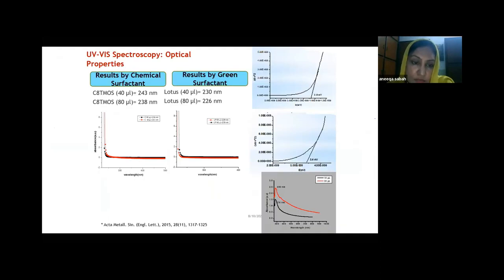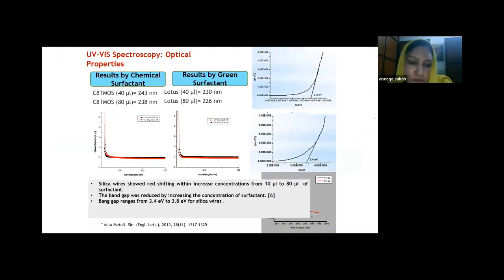We can see absorption peaks, and the silica wires showed red shifting with increased concentration, from 10 microliter to 80. We used two types of surfactant concentration after a hit and trial method to get the best result. The band gap was reduced by increasing concentration, ranging from 3.4 to 3.8 electron volt for the silica wires.